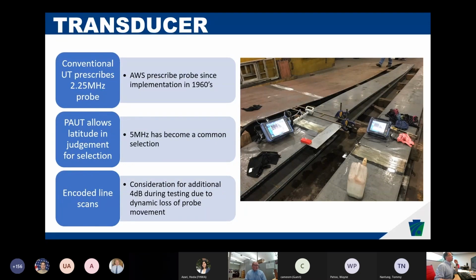So you have to account for when we're actually doing a parallel scan, line scan, are we losing some of the dynamic scanning gain because we're no longer manipulating the probe side to side. So it's not currently in the code, but it's something that needs to be considered for implementation purposes.